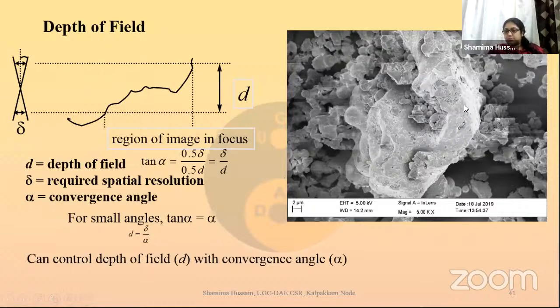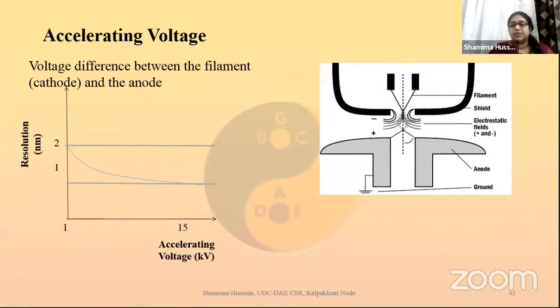So depth of field is at a certain balance where I can tell you by seeing the topography that this is the height of the sample that I have. But this is not a measure of the height. It just gives you a feeling that the sample features are protruding out or going inside. So if I could focus the system in such a way, then I have a very good depth of field. That's how we see.